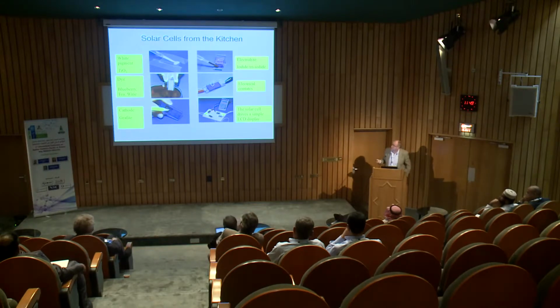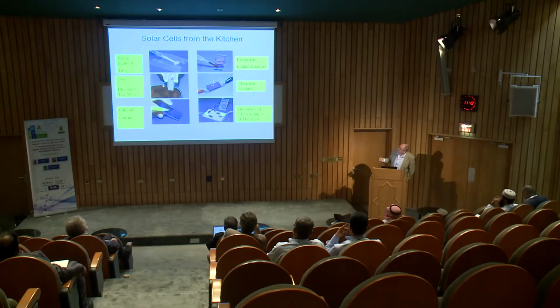And then here is the procedure for how to make a dye-sensitized cell. You prepare a suspension of the nanoparticles of TiO2. You put a drop on the conducting glass. This is our contact for the anode. You have the scotch tape here, which makes a certain thickness of the TiO2 and also masks the electrical contact for later. You have a heat step here where you sinter the nanoparticles together, so you form a nanoporous layer of the titanium dioxide film.